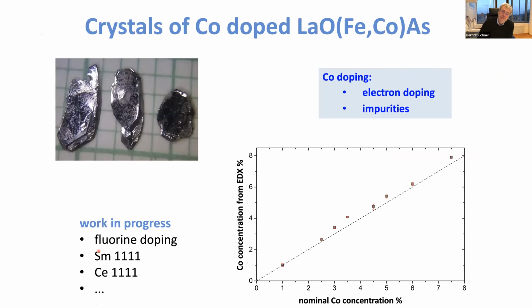So what we managed to do so far is crystals of a series of cobalt doped lanthanum oxygen, so lanthanum 1111. Cobalt doping means electron doping. This we know from the other systems, but it means also impurities. And I've shown you the figure of this manganese doping. That also means that we are not expecting the best crystals. We do not expect the best superconductors because we have intrinsically impurities in there, and they play a crucial role. But that's okay. That's a challenge for crystal growth, and the thing we managed. And here we can do it up to rather high concentrations. We can really control the stoichiometry. Therefore, that was the first series of samples which we studied.